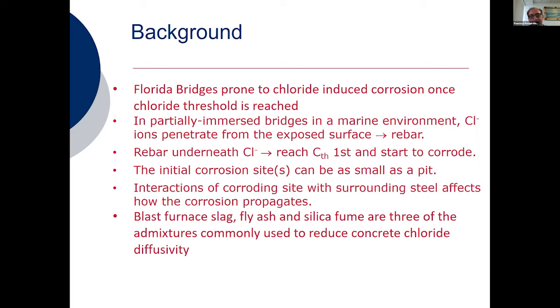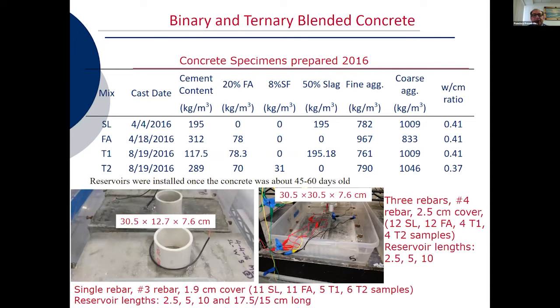Here in Florida, we use a number of supplementary cementitious materials, such as blast furnace slag, fly ash, and silica fume. They have been used for a number of years. In this particular research, we look at these three SCMs in binary and in other cases ternary compositions. We add them as a way to try to reduce the diffusivity of the chlorides going into the concrete. We use two different types of specimens. Single rebar specimens are about 30 centimeters by 12 by 7.5, and they have a concrete cover of 1.9 centimeters, whereas the others contain 3 rebars. I forgot to mention that for the single rebar specimens, a number 3 rebar was used, whereas for the 3 rebar specimens, a number 4 reinforcement was used.